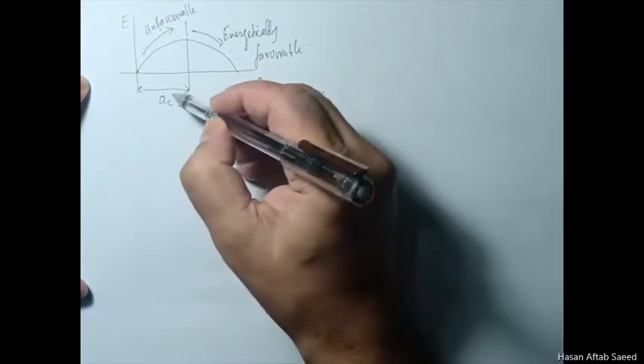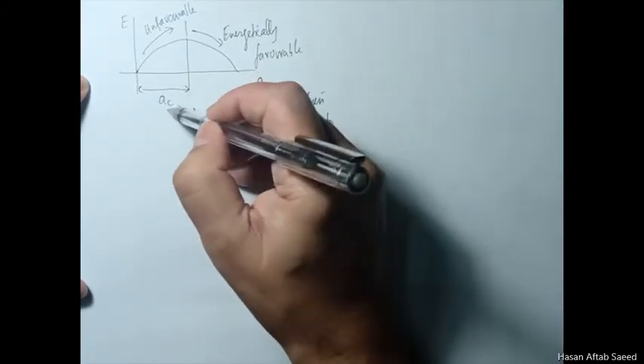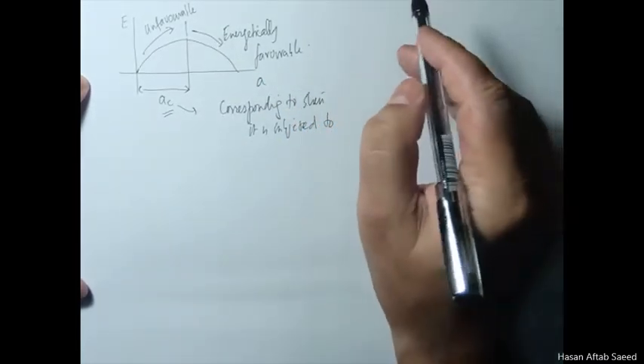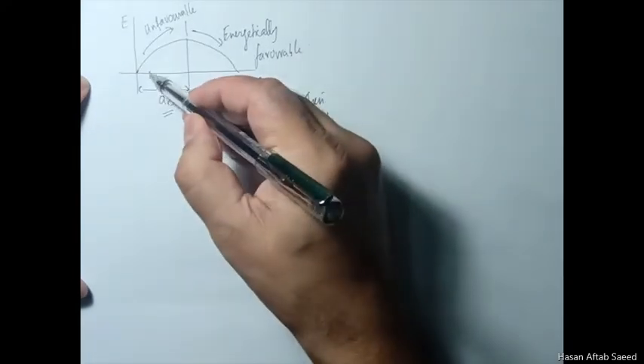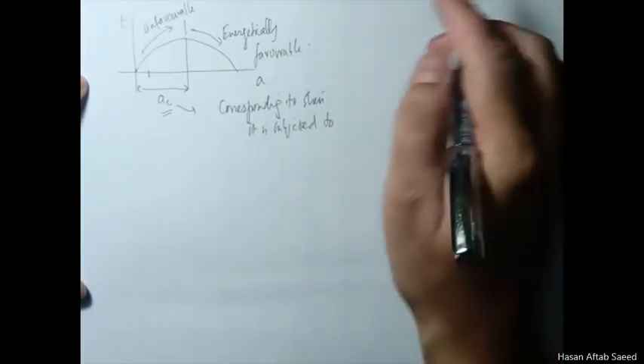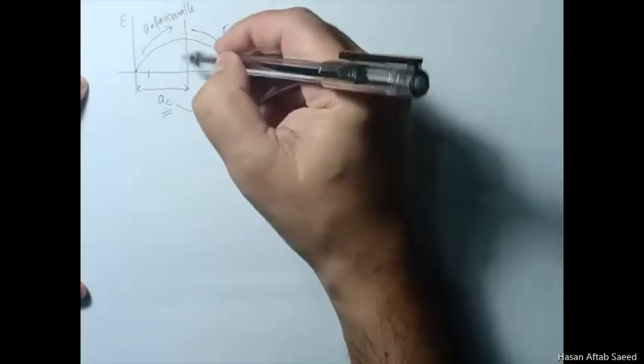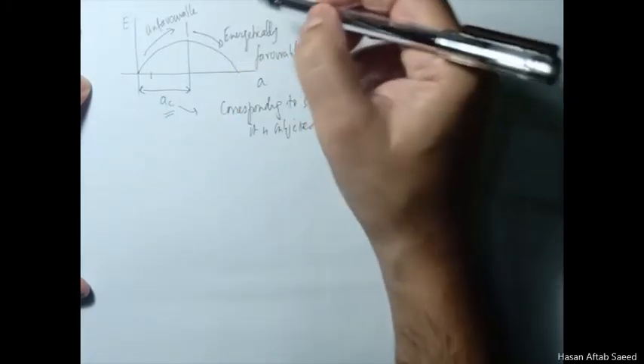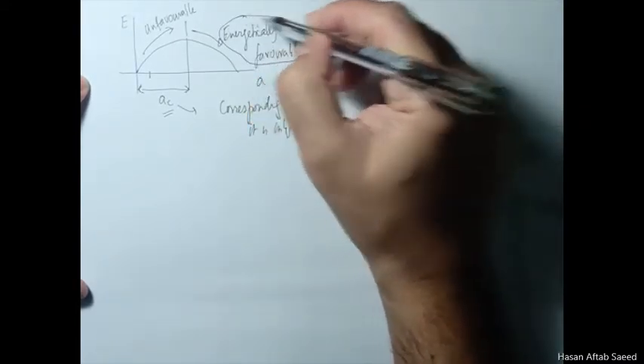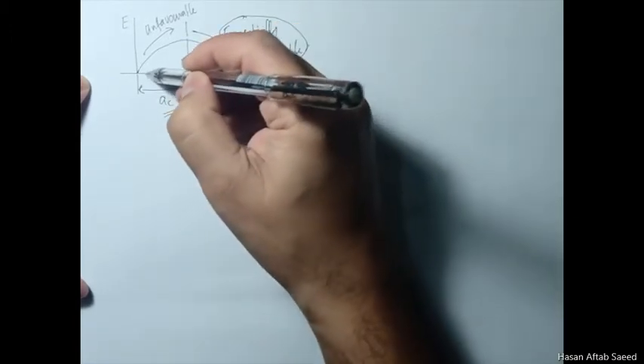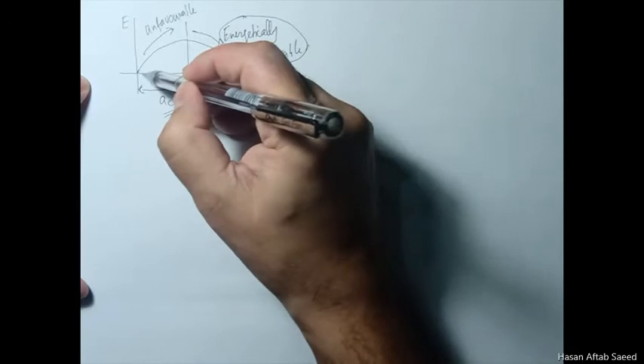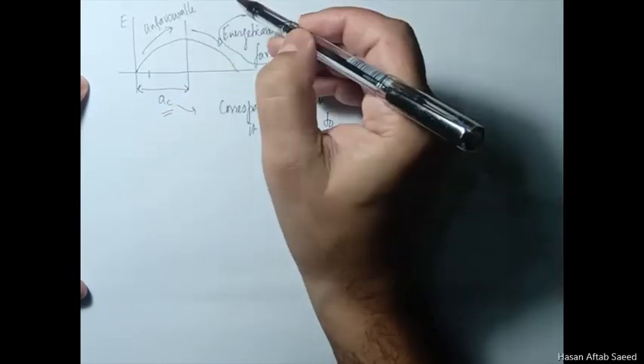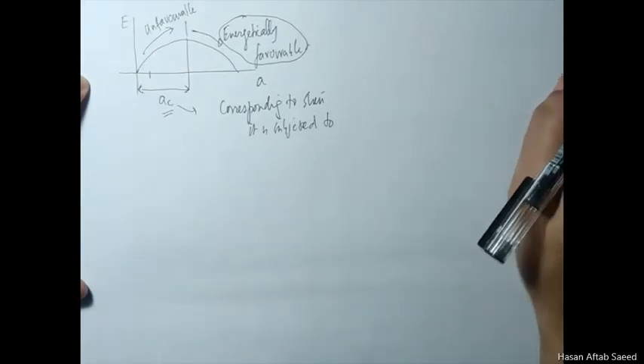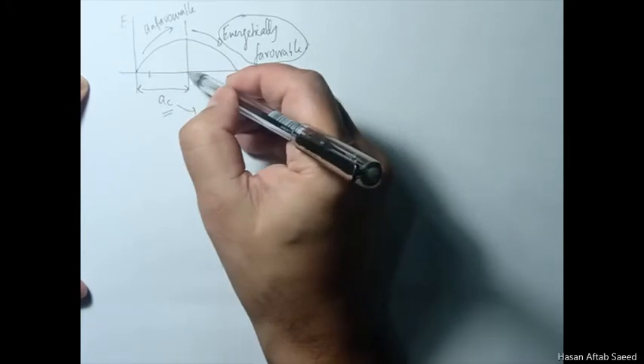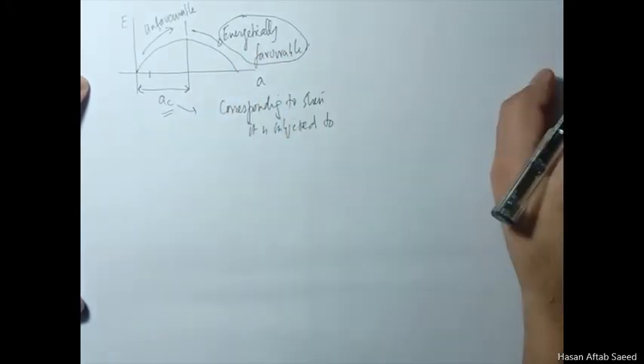We have seen in the previous classes that for a material to undergo brittle failure, that is failure without any warning, the crack length in it must be equal to AC, corresponding to the stress it is subjected to. For subcritical crack lengths less than AC, there shouldn't be any worry about the material breaking catastrophically, because the moment this crack achieves AC, the critical crack length, after that, uncontrolled crack extension is energetically favorable, so nobody can stop it. But before that, in case of subcritical cracks, the process of taking a crack from subcritical level to critical level is energetically unfavorable. So a crack that is smaller than the critical crack should never become as large as the critical crack length. So there shouldn't be anything to worry about.